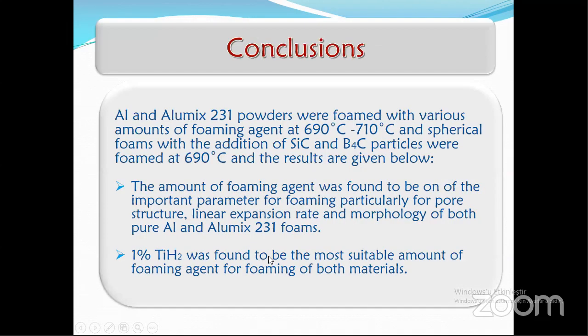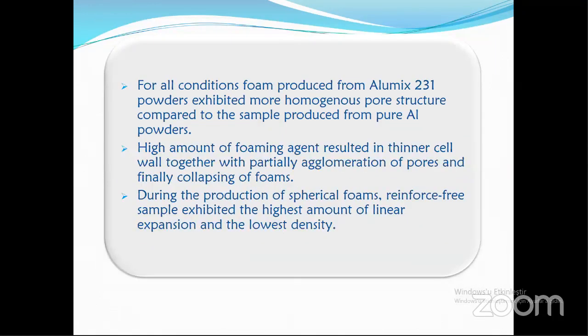Okay. As a conclusion, aluminum and Alumix 231 powders were foamed with various amounts of foaming agent at 690 and 710 degrees centigrade, and spherical foams with the addition of silicon carbide and boron carbide particles were foamed at 690 degrees, and the test results are given below. The amount of foaming agent was found to be one of the important parameters for foaming, particularly for pore structure, linear expansion rate, and morphology of both pure aluminum and Alumix-231 foams. 1% titanium hydride was found to be the most suitable amount of foaming agent for foaming of both materials.